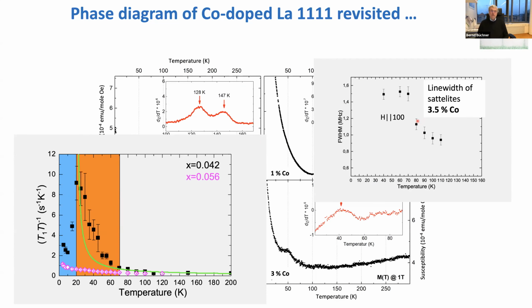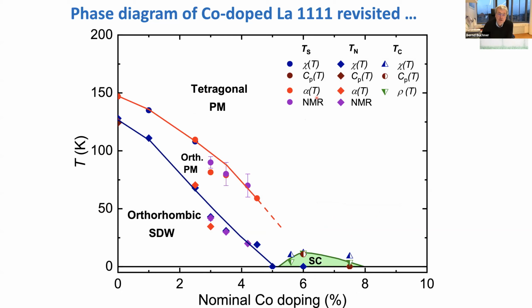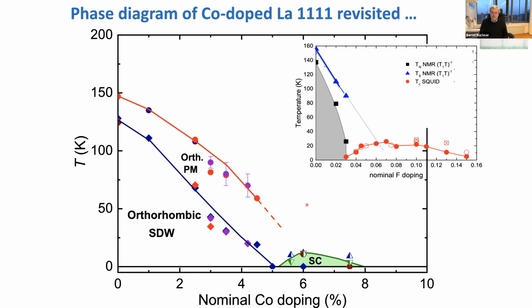So at the end of the day, we end up with the following phase diagram, which shows again the splitting between nematic and magnetic phase transitions, with decreasing temperatures. We lose the signatures of the structural and nematic phase transitions at about 4%. We can follow the magnetism down to these concentrations, and then superconductivity emerges. That's qualitatively very similar to this phase diagram. Maybe it's a little bit broadened in this region, but of course we are now discussing compositions in the second digit of the cobalt concentration. So that's the phase diagram, and it's somehow similar to what we know for fluorine doping, with a suppressed Tc due to cobalt impurities.